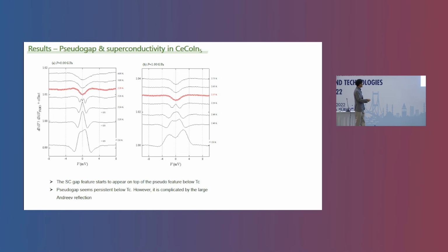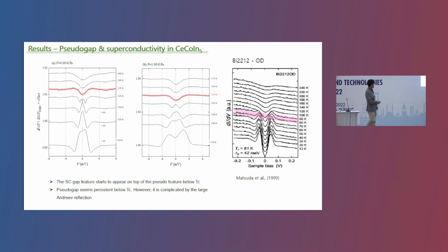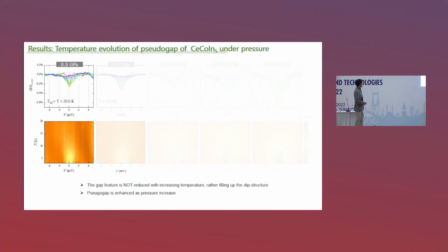At higher pressure, you can see a similar feature, and this feature is pretty similar to what you observe in high-Tc cuprates. In high-Tc cuprates, this is STS, measuring tunneling, so you do not see Andreev reflection enhancement, but rather you see enhanced suppression and also the coherence peak. Okay, so this is the temperature evolution of the pseudogap.